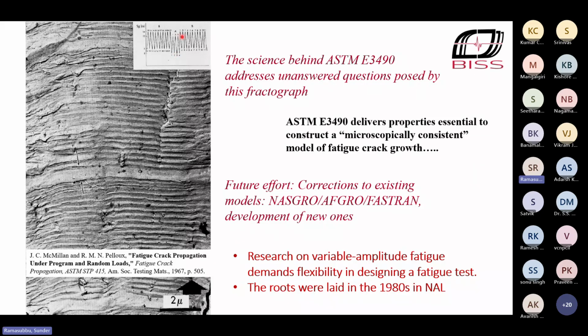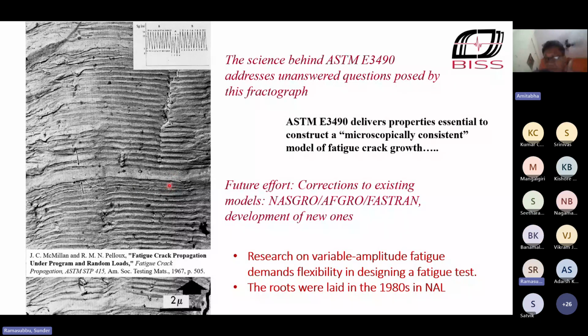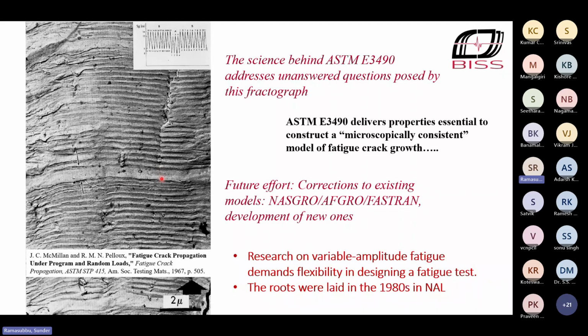So what is it that caused that change? Nobody has been able to explain. McMillan and Pelloux, in their original work, they said it had to do with the crack tip sharpening and blunting. But that model is discredited because it doesn't explain the other things you see over here. One of the other things you see over here is this jump in crack size when the load goes up from here to there. The load has just gone up by about 28%. But the jump in crack size in the crack front is huge.